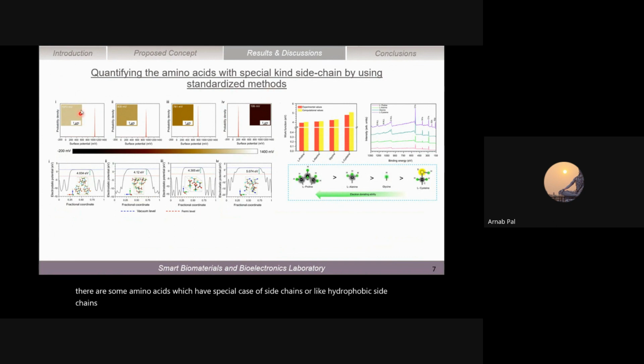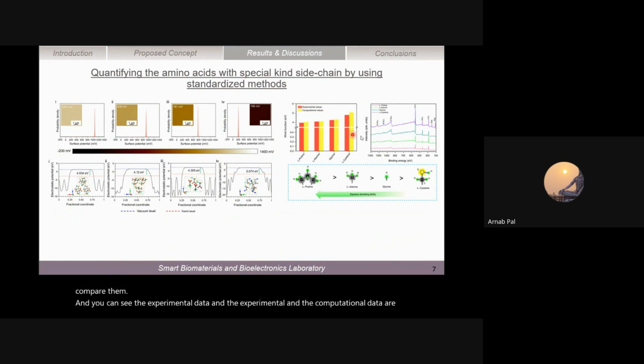So here you can see that I did the KPFM. This is the KPFM data, and this is the work function data I simulated using DFT, density functional theory. And here you can see I compare them, and you can see the experimental and the computational data are very close to each other.